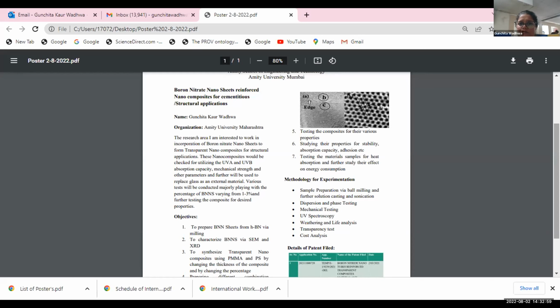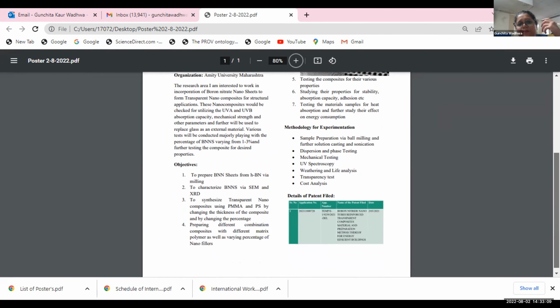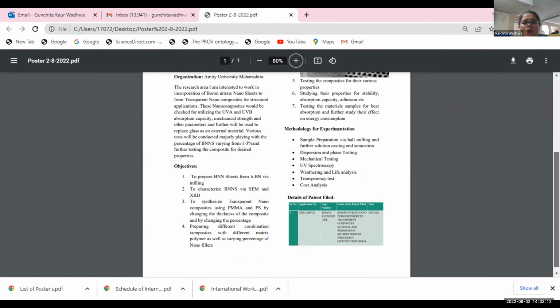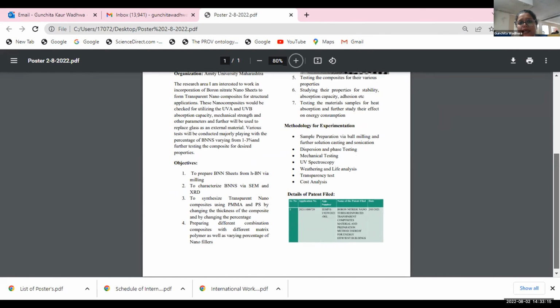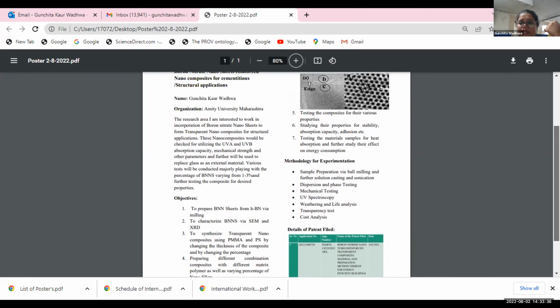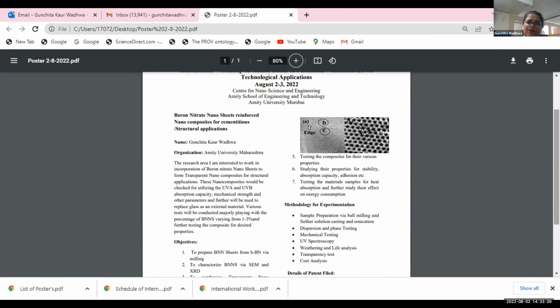So I had selected two polymers, that is polymethyl methacrylate, that is PMMA, and polystyrene. So what I'll be working on is majorly, firstly, preparing boron nitride nanosheets from hex boron nitride via ball milling process, 20 hours of milling, and further seeing whether these boron nitride nanosheets have been achieved. Then I would be incorporating them, playing around with the percentage as well as the thickness. So the thickness may vary from 1 to 5%. And then I'd be studying what exactly will be the effect and implications. And firstly, characterization will only come into picture if I have to see my nanomaterial is distributed throughout.